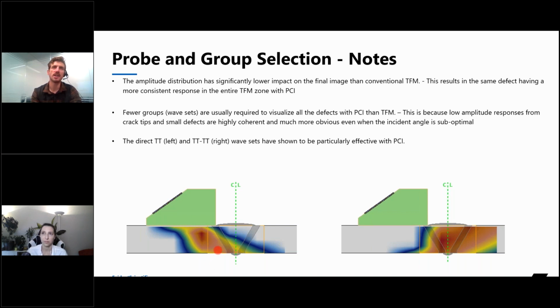So anywhere where I do have a color distribution right up into here is still going to be valid using PCI. With TFM, when we're getting these low amplitude areas, it might be a bit more difficult to see the image, or you might have inconsistent imaging from, say, this bottom corner versus this bottom corner, because the amplitude is much lower. But with PCI, we're going to get a good distribution throughout the entire part. Up in the top corner here is probably not as valid, just because logically with a TT group, we'd have almost no sound getting to that point. With our TT-TT group, same idea, but here with TT-TT, we can pretty much cover the entire part.